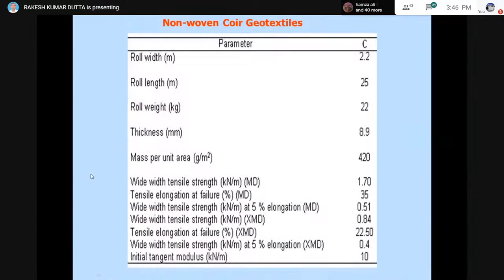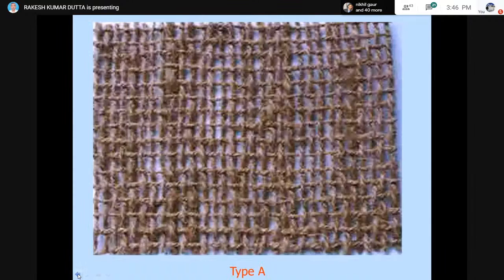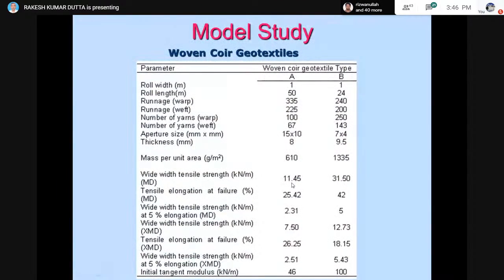Then we have used one non-woven type of material which we call type C. And if you look at the tensile strength of the type C material, it is only 1.7 kilonewton per meter. But the tensile strength of type B is 31.5 and type A is 11.45. So you just keep this tensile strength in mind.